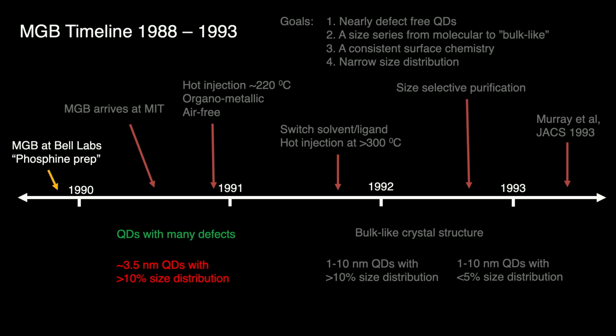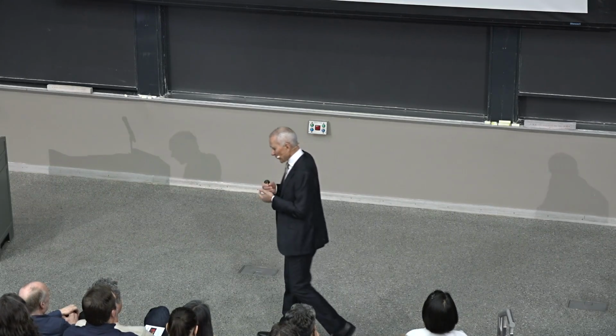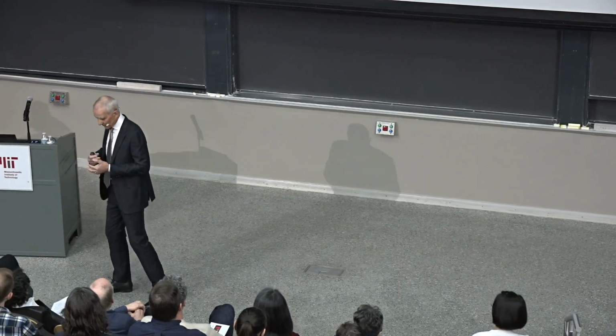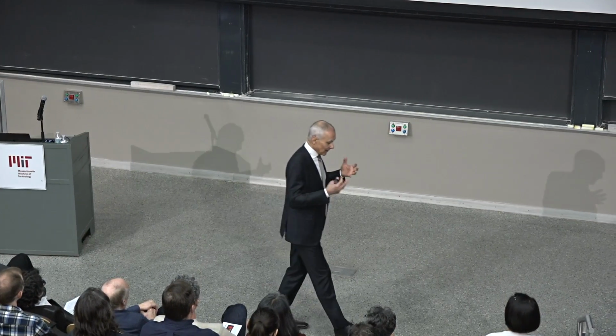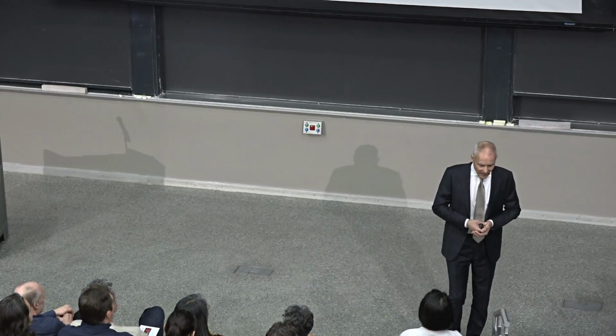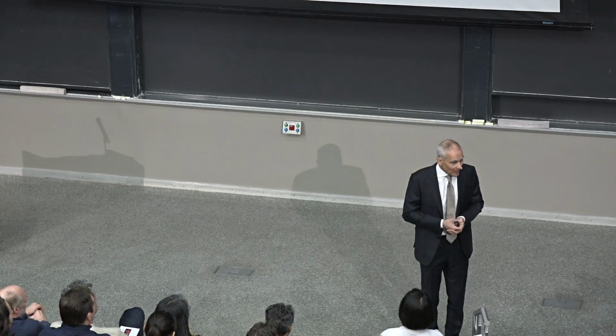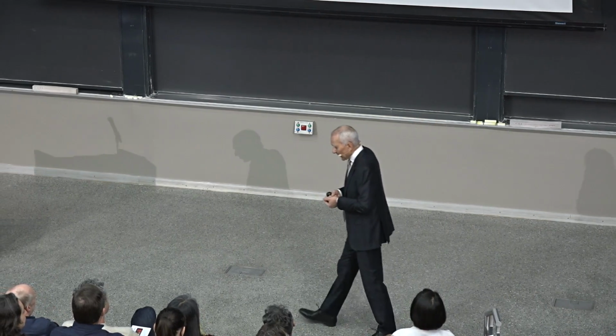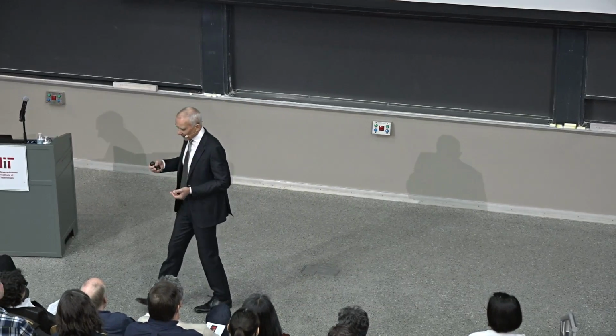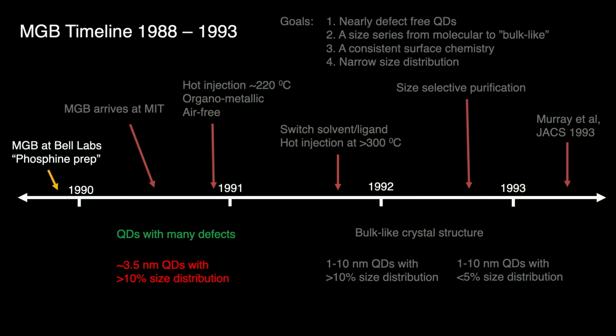So I go back as a postdoc, and my first assignment as a postdoc with Louis is that Louis and Mike Steigerwald and Paul Vasados, who had been postdoc right before me, had found that if they took the particles that they were making at the time in pyridine, which is what we call today a Lewis base, and cooked it up, boiled it, the absorption always looked the same. And it was very sharp. It was more like a molecular absorption. And they thought maybe what was happening is that what they were creating was what we called a charge transfer species, where there was an electron going from the quantum dot to the pyridine on the surface. And maybe that was the case. So that was my first assignment.